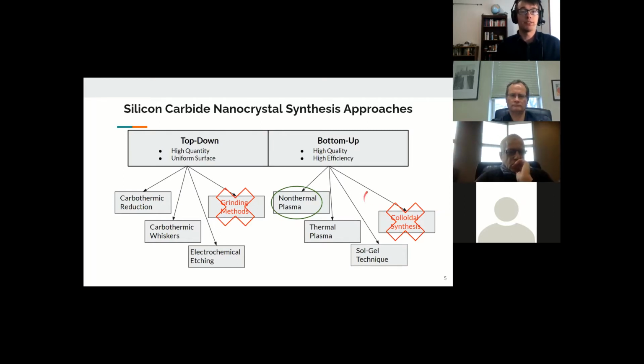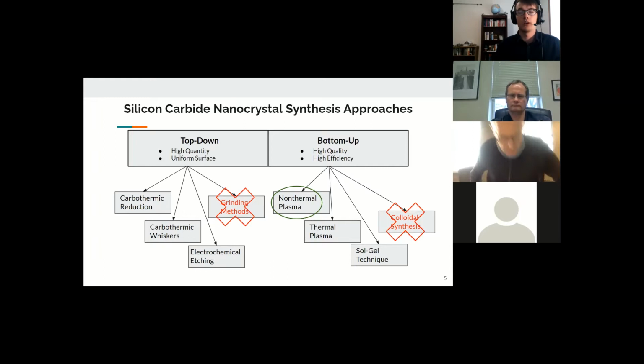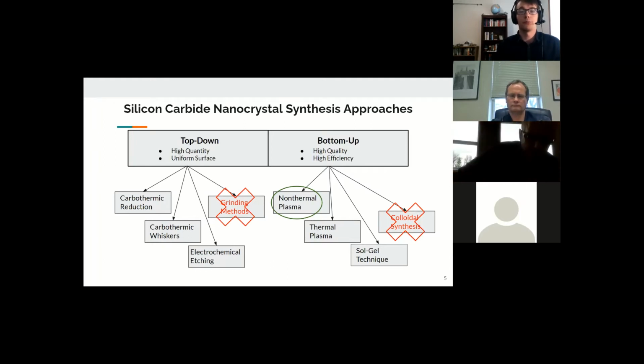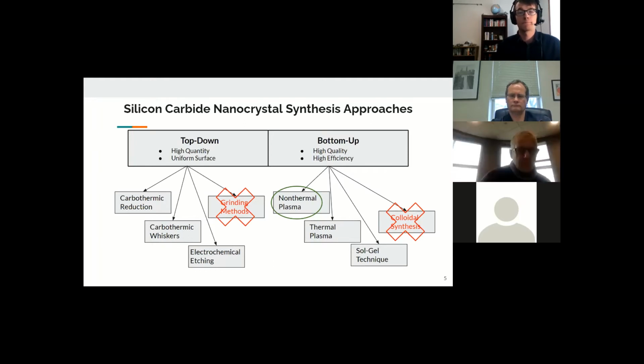Unfortunately, perhaps the biggest synthesis technique that's missing from silicon carbide research, which many other semiconducting nanoparticles have as an option, is liquid phase colloidal synthesis. It's not feasible for silicon carbide because the precursors would have to be very unstable and highly exothermic to be able to form silicon carbide, which is very stable. Thus, alternative synthesis techniques must be explored for silicon carbide.